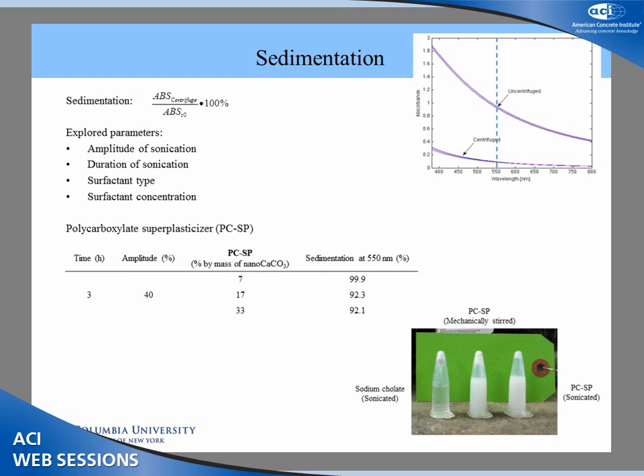And we explored a number of different parameters, including amplitude and duration of sonication, and also surfactant type and surfactant concentration. And you can see in the lower right that some surfactants just were not effective at all. After centrifugation, it ran clear, so there was no dispersing capability whatsoever. One of the more effective ones, or the most effective one, was the PC superplasticizer. This sample wasn't even subjected to sonication, just passively, very gently stirred, but the surfactant was effective in stabilizing some of the particles, although some of it did crash out. And with sonication, it was improved.